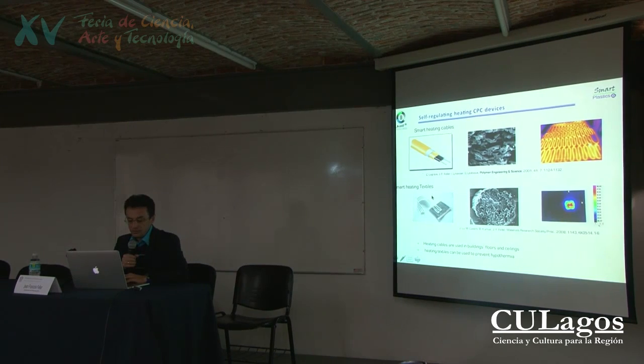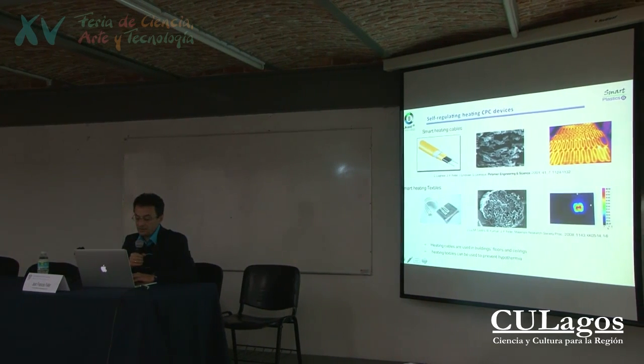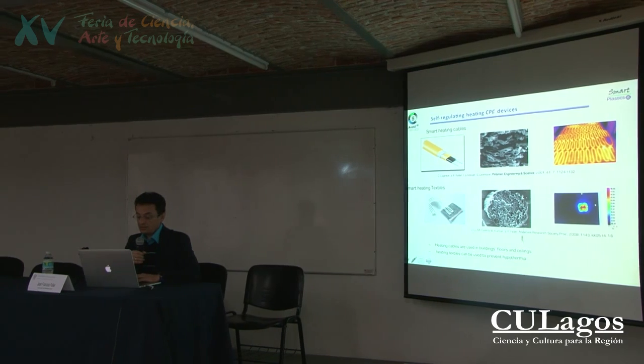It's possible also to use such material to make intelligent textiles. You have here a fiber made of nanocomposite, which is able to heat, to warm. So you can imagine textile made of these fibers able to warm, to prevent hypothermia, for example. You can see here that these fibers has been weaved. And such fiber can be sensitive also to chemicals. So you can use them to analyze chemicals on cloths. It has been done for firemen to prevent them from being burnt by the fire.